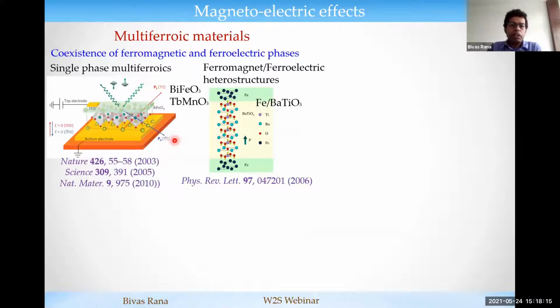You know about multiferroic materials, and you are quite familiar, I guess, with this slide also. In a single phase multiferroic material, ferromagnetism and ferroelectric phases coexist. So by applying an electric field, you can tune the magnetic property and vice versa. Alternatively, you can make a heterostructure. For example, you can put a ferromagnet on top of a ferroelectric material, and if you apply an electric field to the ferroelectric material and induce electrical polarization, then at the interface this electric polarization interacts with the magnetic moment of the ferromagnetic material, and that is how you can tune the magnetic property of the ferromagnet.